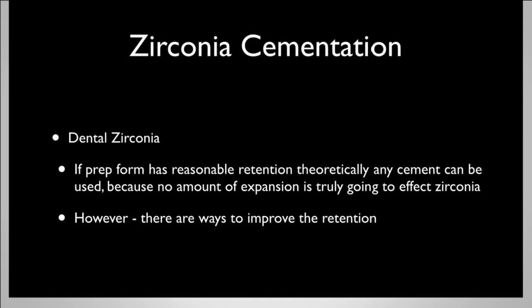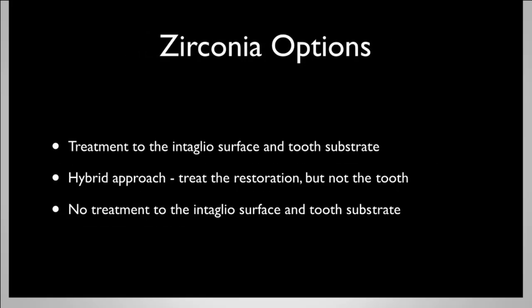Now there's other ways to cement things, especially with zirconia. When it comes to zirconia, things can be as simple or as complicated as you want to make them. With proper preparation form, you can literally use any cement that's out there, including zinc phosphate. So if you like to mix powder and liquid, you're welcome to use it. It will work with zirconia, as long as you have traditional retentive properties. However, there are always ways to improve things further. So with zirconia, we can treat the intaglio surface, or underside of the restoration, as well as the substrate. We can use a hybrid approach where you treat the restoration but not the tooth. Or we can do no treatment at all and just cement as usual. All those become possibilities, and this is simply based on retentive properties.